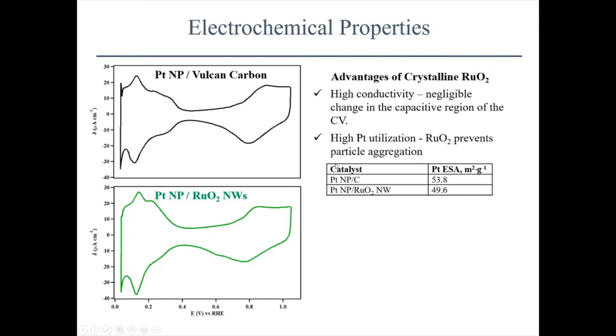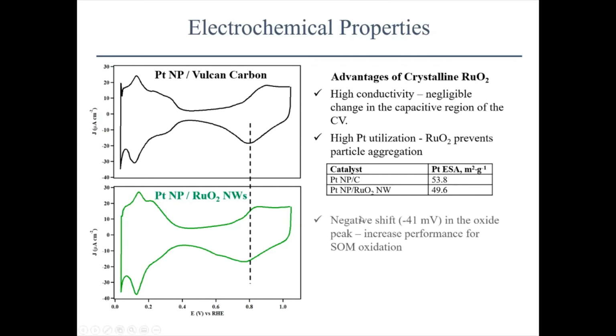Another thing that might be a concern is, do we get the same platinum utilization when we use a different catalyst? And we did ICP-MS to extract out the platinum loadings on both catalysts. ICP-MS is inductively coupled plasma mass spectrometry. And we saw that basically both catalysts gave essentially the same platinum utilization, about 50 meters squared per gram. So we didn't see any deleterious effects from the ruthenium oxide on utilization.